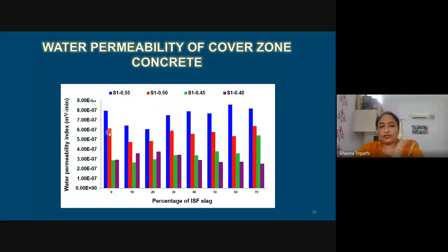However, one more interesting point is that there is no difference, or only a marginal difference, between the control and the concrete which has the highest replacement of 70%. There were a few specimens which had higher than control. The green bars, if you see, this specimen has more than control permeability. Okay, so we will discuss it later because I have one more parameter to discuss on permeability. The reasons I will discuss collectively.